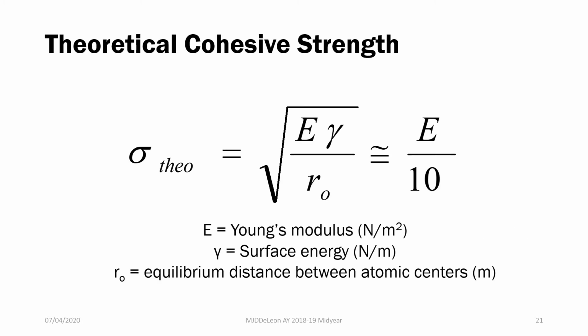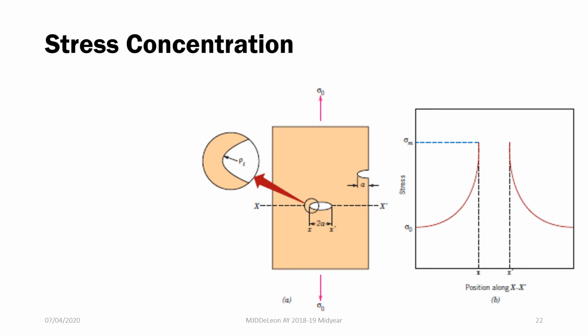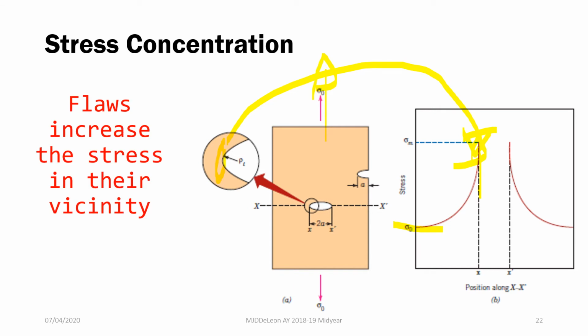So the theoretical cohesive strength of a material can be approximated as 1/10 of the elastic modulus of your material. But as we've seen before, the strength of a material is much less than this theoretical cohesive strength due to defects in your material. This is due to the phenomena which we call stress concentration. When we have a crack, nagkakaroon ng tendency na in this region here, in this crack here, yung stress na ma-experience niya would be much higher than the applied stress in the material. So flaws increase the stress in their vicinity.